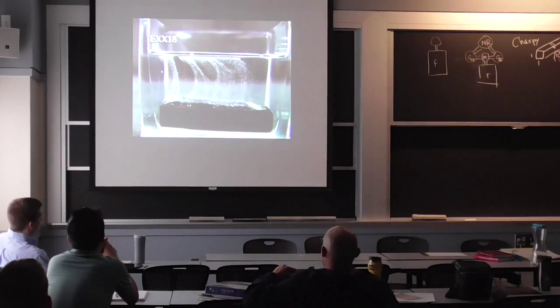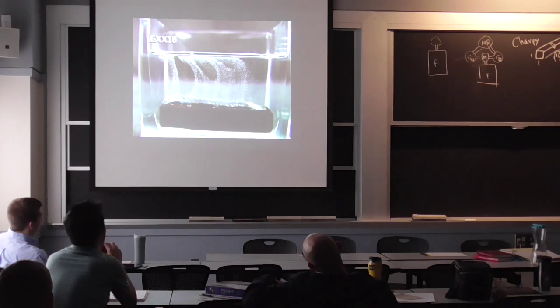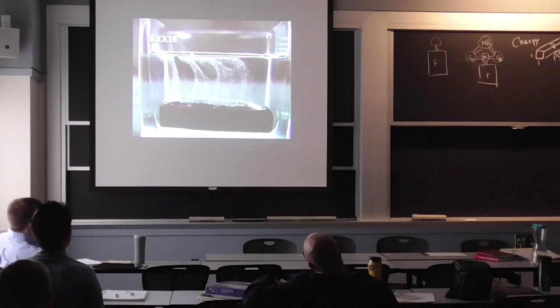The second sample was welded with a low hydrogen electrode. Compared to the first sample, much less hydrogen diffusion is evident. This coincides with the fact that approximately 10 times less hydrogen will be introduced to a weld made with low hydrogen electrodes compared to traditional cellulosic-coated electrodes.